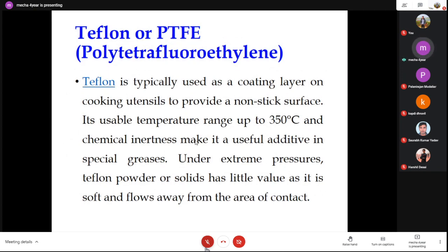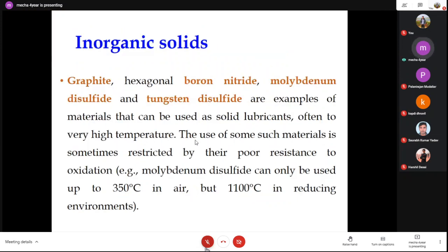Teflon is typically used as a coating layer on cooking utensils to provide a non-sticky surface. Its usable temperature range is up to 350 degrees Celsius, and its chemical inertness makes it a useful additive in special greases. Under extreme pressure, Teflon powder or solids have little value as they are soft and flow away from the area of contact. Inorganic solids like hexagonal graphite, boron nitride, molybdenum disulfide, and tungsten disulfide are examples of materials that can be used as solid lubricants, often to very high temperature. The use of some such materials is sometimes restricted by their poor resistance to oxidation. Molybdenum disulfide can only be used up to 350 degrees Celsius in air, but 1100 degrees Celsius in a reducing environment.